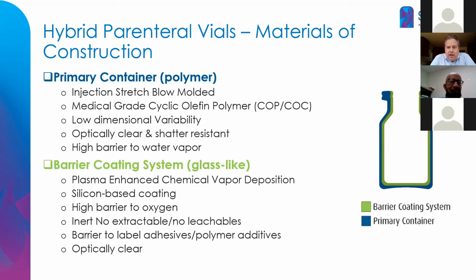Also, cyclic olefins have a fairly high barrier to water vapor, so they keep water out or in, depending on the application. And then on this container, in a separate process, using plasma enhanced chemical vapor deposition, we deposit a very thin glass-like coating. It's silicon-based. It provides enhanced barrier for atmospheric gases, in particular oxygen. And another important feature is that it's a clean, inert environment where there are no extractables, and leachable studies with drug product have shown little or low leachables.